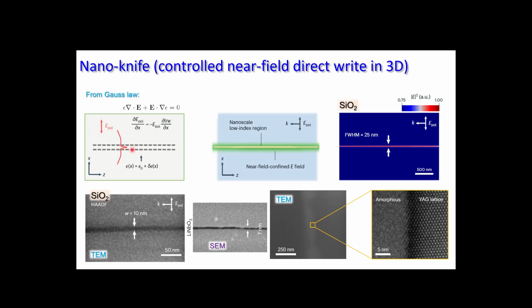So somehow it's the same as in ablation of titanium film. So if you have slowly decreased refractive index on the optical axis, it will be the place where light will be happily localized and absorbed. And it's also not a propagating beam, so it's really light which is localized. Intensity is increased. It's really modifying this nano volume.